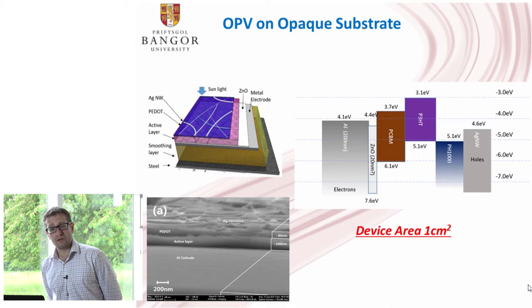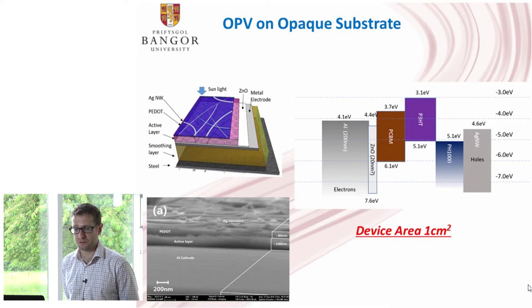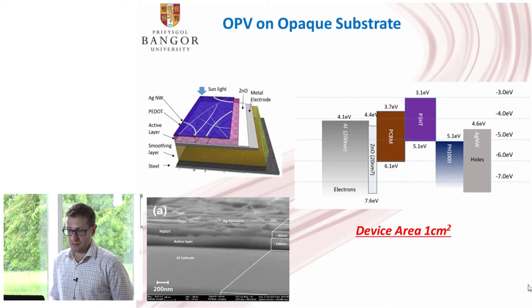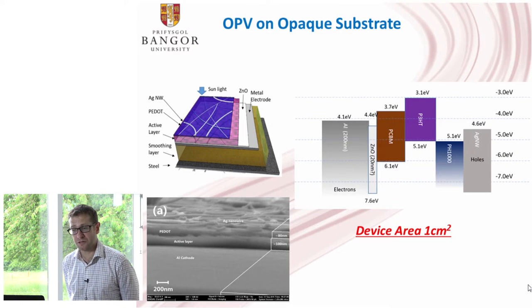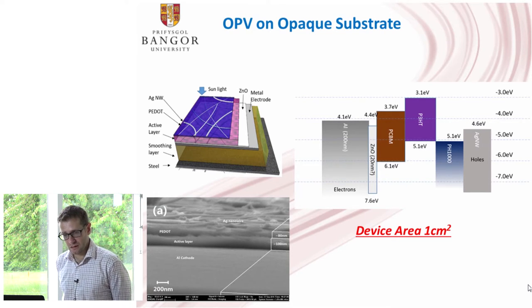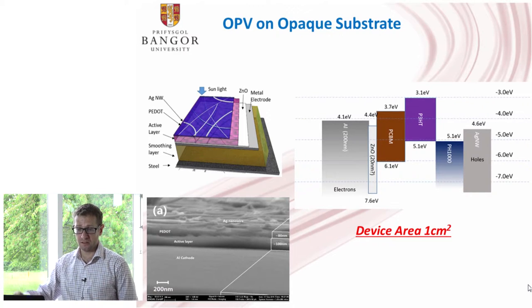This is the configuration we use for manufacturing an organic solar cell on an opaque substrate. We start off with our steel substrate. We then apply a planarization layer, an intermediate layer, which consists of SU8. On top of that, we deposit our back electrode, which could be silver or aluminium. We then apply our electron transporting layer, which is zinc oxide, our active layer, and finally the composite top electrode. Light comes into the solar cell through the silver nanowire electrode, and it's absorbed by the P3HT:PCBM active layer. Shown here is a cross section of the device, and you can see the various layers, including the cathode, active layer and P-dot, and the nanowires on the surface of the device.